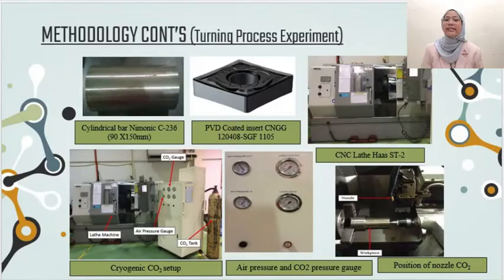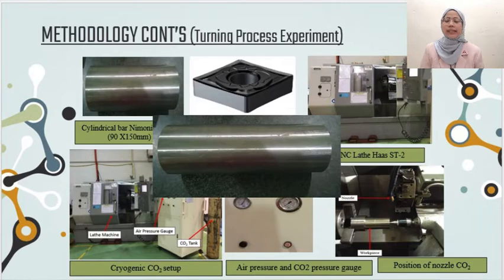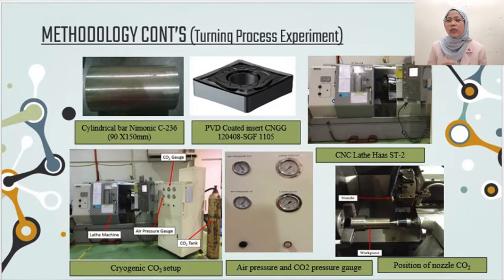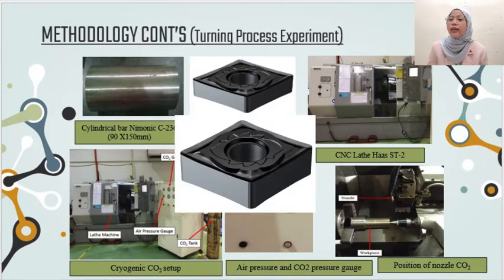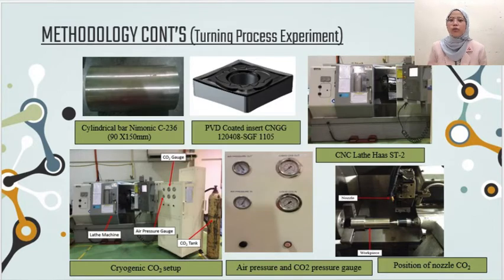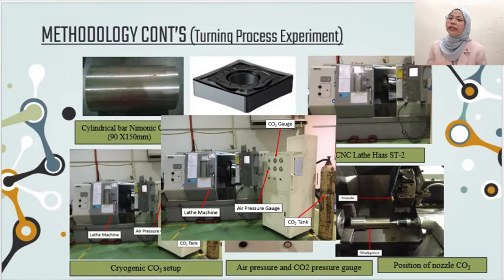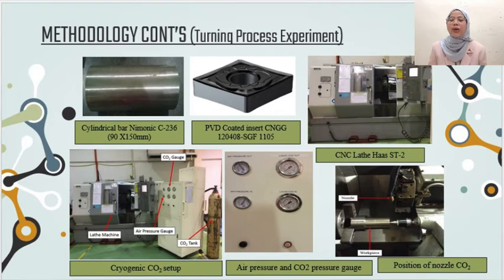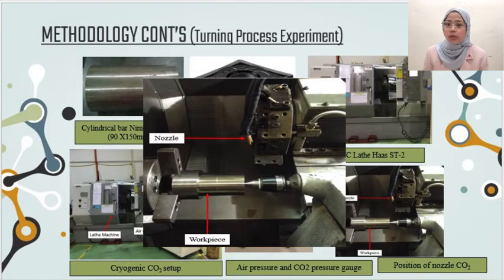Here is objective 3. It's the turning process experiment. The Nimonic C-263 has a diameter of 90 mm and a length of 150 mm. The cutting tool used in this experiment is a PVD coated carbide insert. This PVD tool is attached to the tool holder of the CNC lathe ST-2 machine. Then set the cutting parameters that have been arranged in the RSM Box-Behnken. Then a cryogenic coolant system was developed to supply liquid carbon dioxide CO2 as a coolant. In this experiment, the CO2 coolant is supplied directly to the cutting zone through a nozzle to reduce the cutting temperature during the machining process.